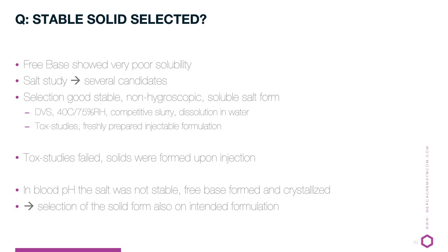So additional tests were done and we checked what was actually the case. We knew that it was an injection in blood, and the blood pH shows that this salt was not stable. The free base was formed and it crystallizes out. We should have gotten a different selection of the salt if we had known that the formulation would have been an injectable. So selection of your form is also depending on the intended formulation, the route and the dosage.